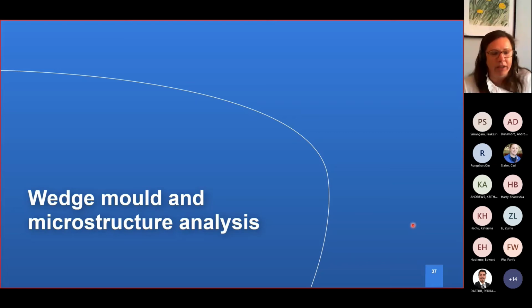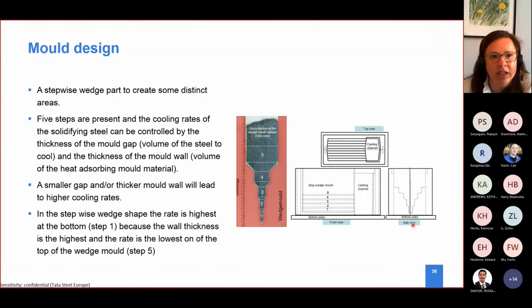Another method, which also has been done with another student from Warwick University, is the wedge mold. We had a static design method of an ingot with different thicknesses, stepwise, to measure different solidification or heat extractions on one single sample. Why is that? Because if we have a new steel and we have several choices of casters, I already explained we have 3 slab casters and 1 thin slab caster. Sometimes with a new steel, we don't know where we are going to cast it, or if it's even able to be cast on all the casters. Could be, but we have to make a choice. Therefore, this is a very good approach.